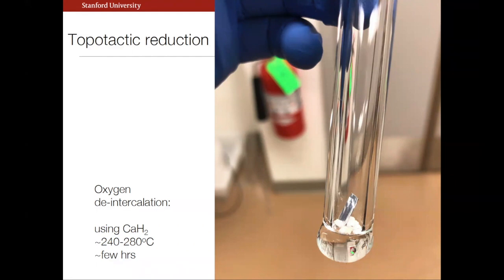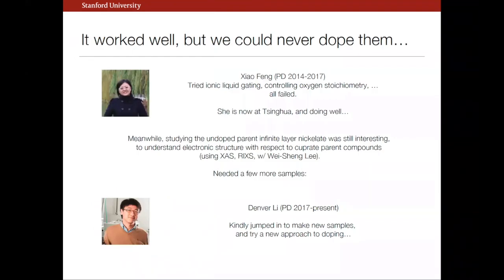So this $5 experiment is actually quite hard. Let me show you some of the people that were doing this. As I said, there was some small but established body of work on this, and we got it to work pretty well, but we could never dope them. This actually has a long history. Xiao Feng was a postdoc with me and made these initial steps, and we tried everything: ionic liquid gating, fine control of the oxygen stoichiometry and geometry, but we could never really get it to work. I should say she's doing well, so it wasn't career ending, but it was quite frustrating.